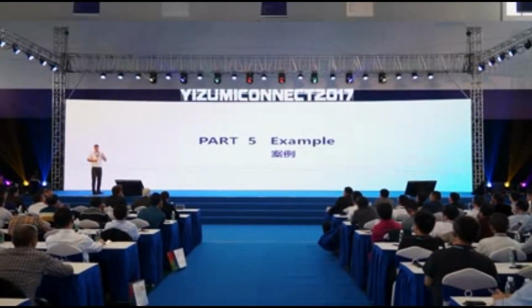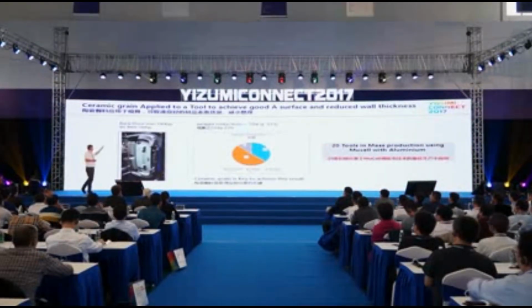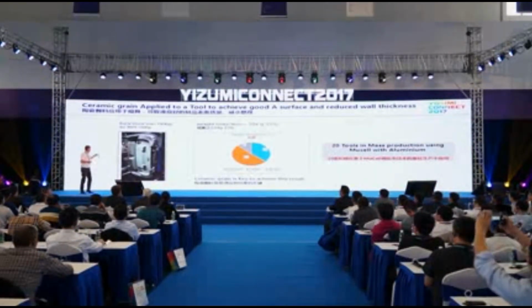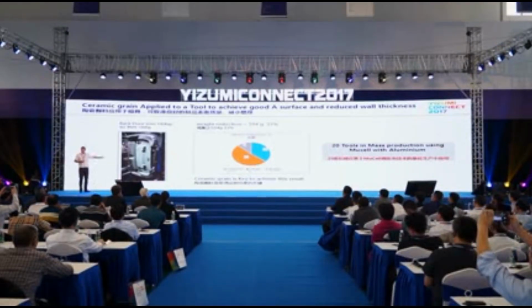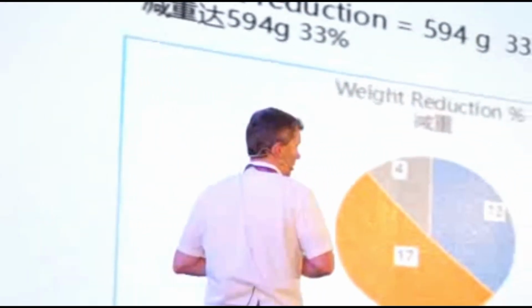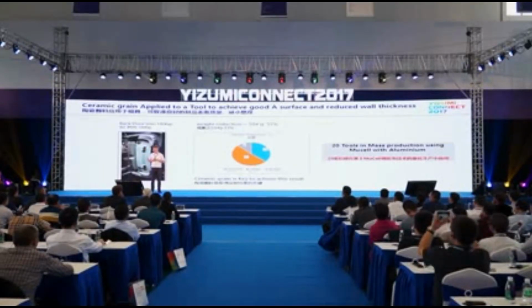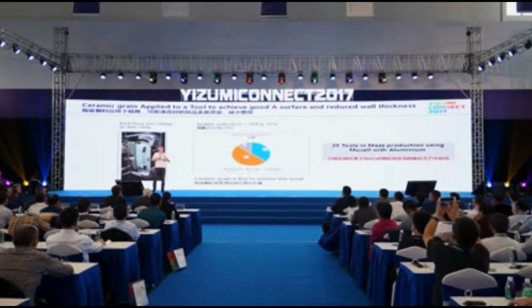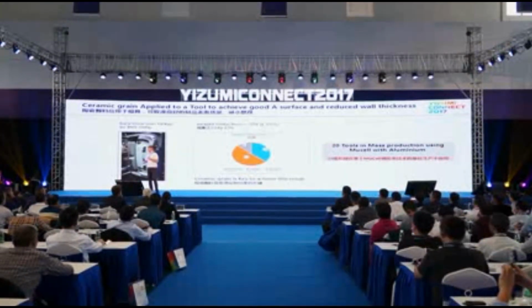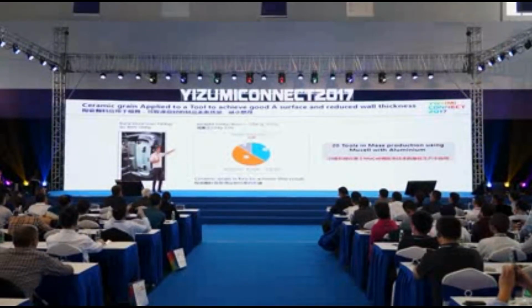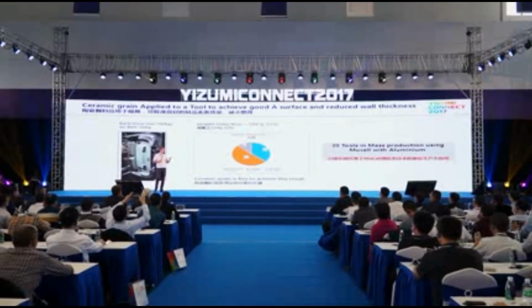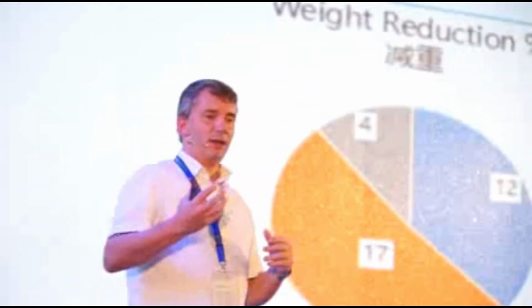So here's an example of one of the activities we did. We took a backdoor trim. It was 1,800 grams, and you can see the texture here is like a grain texture. So it looks a bit strange. We ended up with a weight reduction of 594 grams, which is a 33% mass down. Now, we did that not only from the foaming, and this is the point of view. The foaming allows you to change everything else. So 4% was only by the bubble, what we call the density reduction by bubble. But 17% was by design.